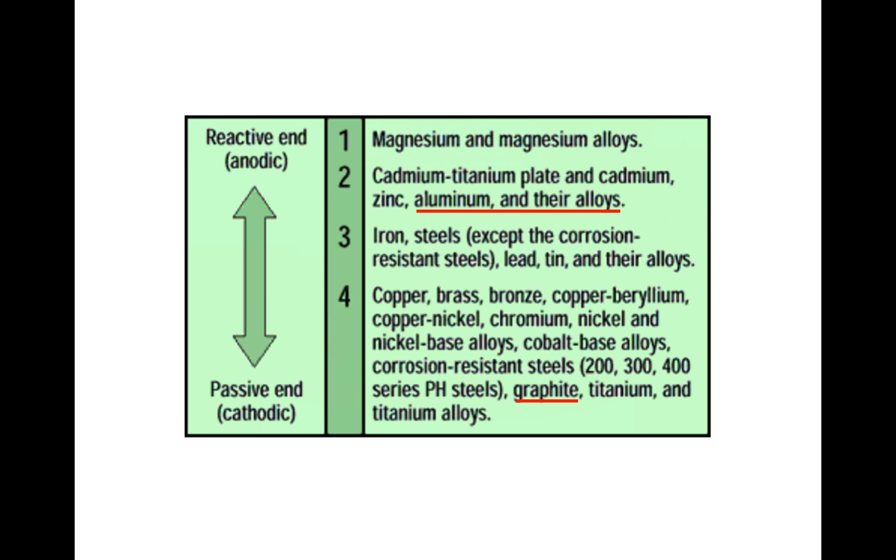What about using nipples other than those made from aluminum alloy? Aluminum is very reactive and when it's in direct contact with graphite, we have a bad situation for corrosion. I would be far better off with brass nipples if I could accept a small amount of increased weight, or possibly using titanium nipples.